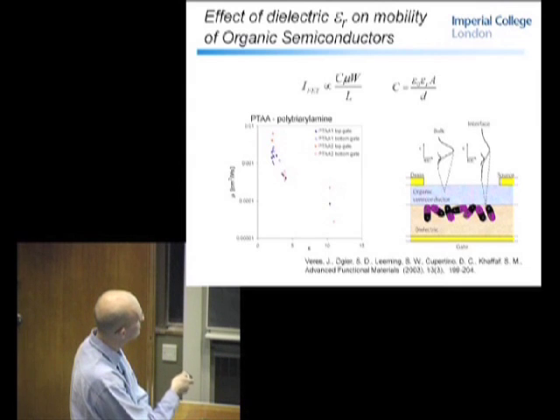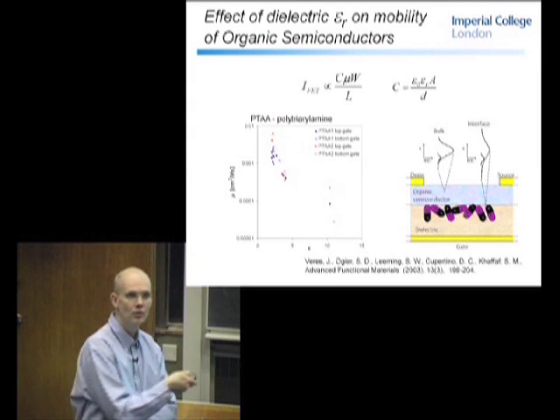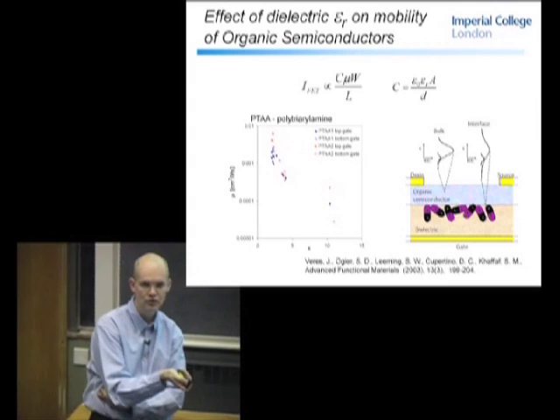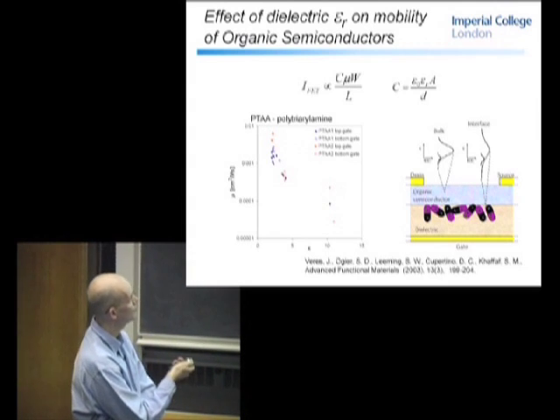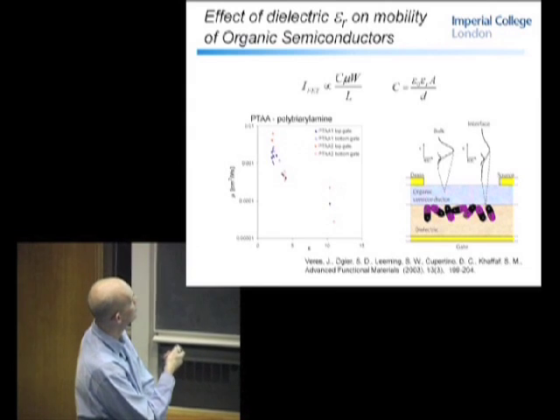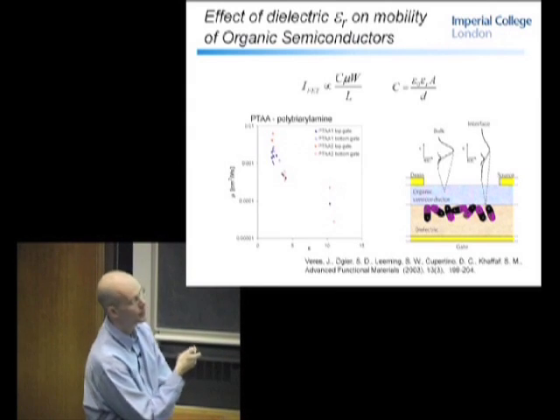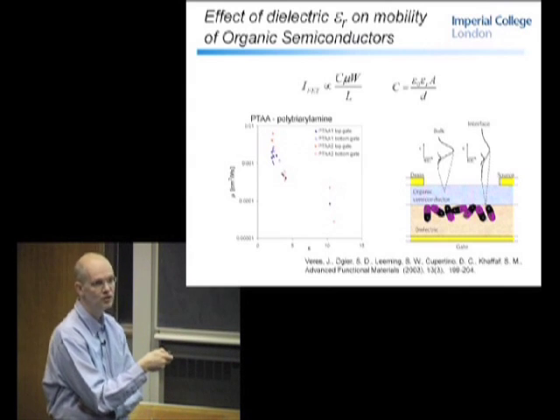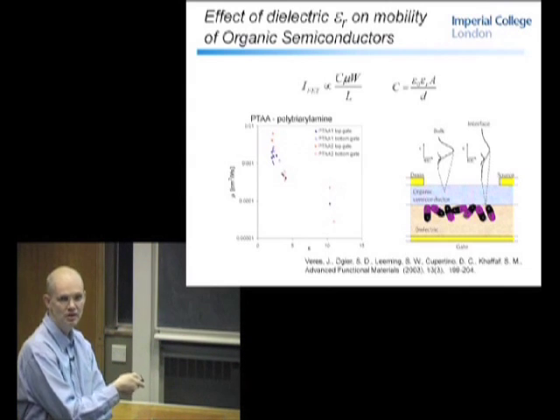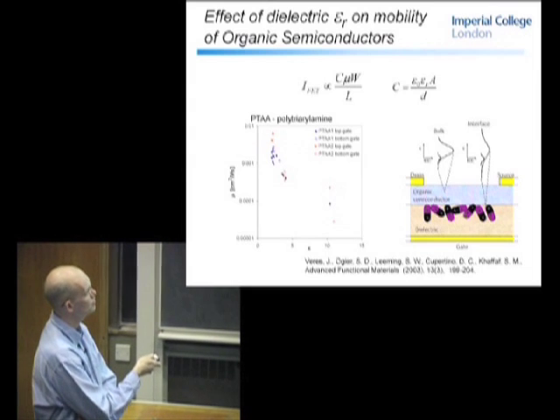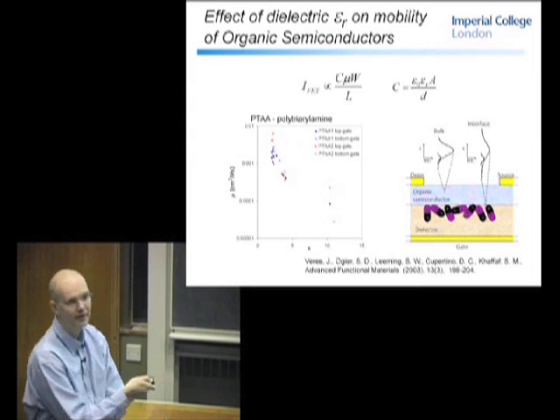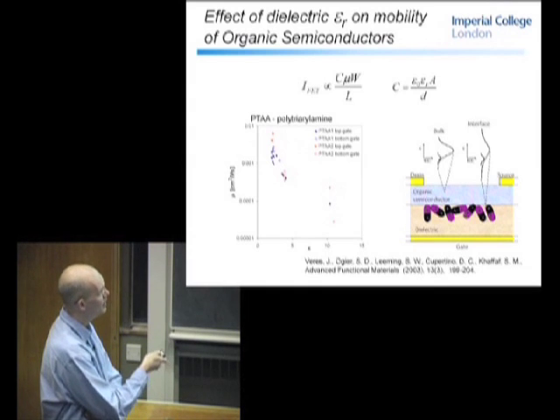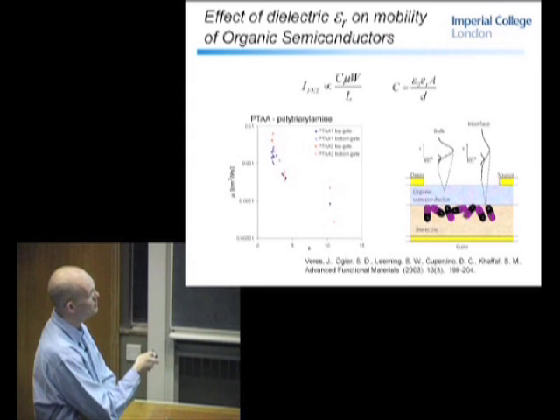You see here this relationship is quite a strong one, that the highest mobilities are with very low K dielectrics, which causes its own problems, because low K dielectrics have low surface energies. Low surface energies are very difficult to spin coat on. And also, if you think about it in terms of capacitance, for low voltage operation, you really want a high dielectric constant. So this observation is really not optimal, and people are starting to think about bilayer, two-layer dielectrics, high K for switching voltages, and then maybe a low K treatment to improve the density of states at the interface.